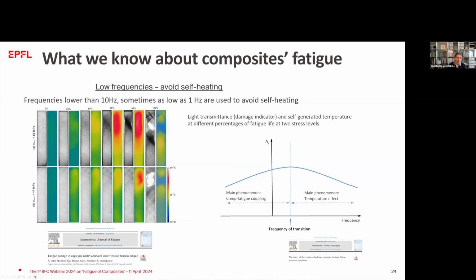So what you see here, the colored plots are thermal camera plots. The black and white is a normal camera showing the damage of the material. And we see the evolution of damage from 0% to 100% of life, so until failure. And we see that damage initiates at specific points. The material becomes darker here, so the translucency of the material is not the same anymore. And at the location where we have damage, we also have an increase of temperature.